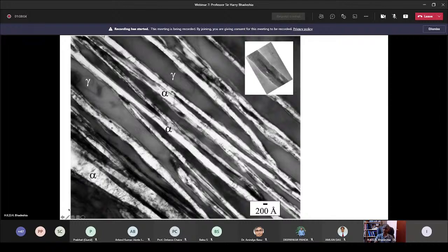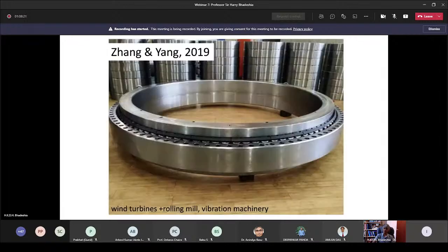And again, we have the mixture of carbide-free ferrite and carbon-enriched retained austenite. So here, the strength is much greater than 2 gigapascals. And one of the first applications of this is in bearings, large bearings. So the rolling elements that you see here, normally we think of them as balls, but they can also be cylinders in shape, are made from this so-called superbainite.